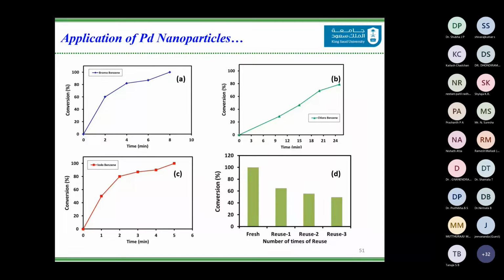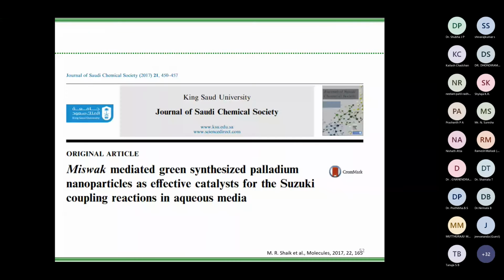Moreover, we reused these palladium nanoparticles several times, and we found that there is a substantial reduction in catalytic activity, which can be due to the deposition, the loss of the phytomolecules that are present on the surface, as well as loss of reactant or catalyst during workup. So we were not able to confirm what was the reason. So this was published in the Journal of Saudi Chemical Society.